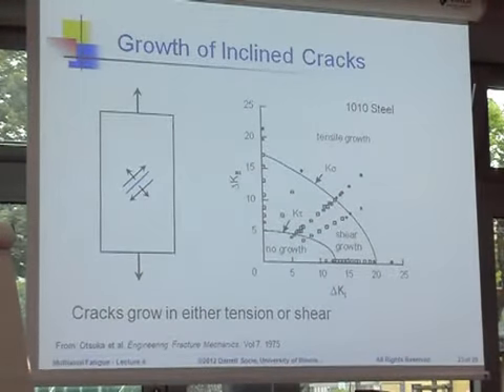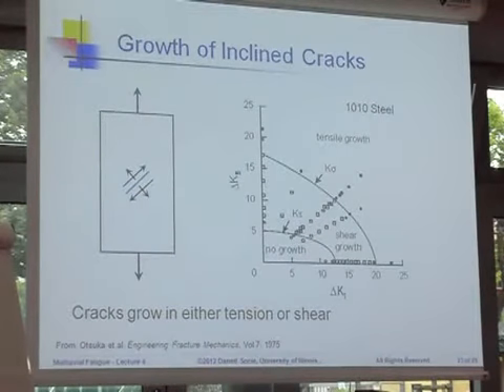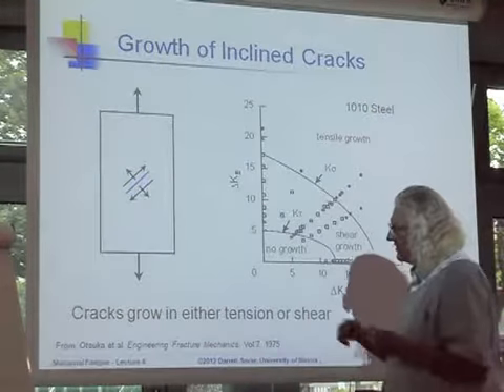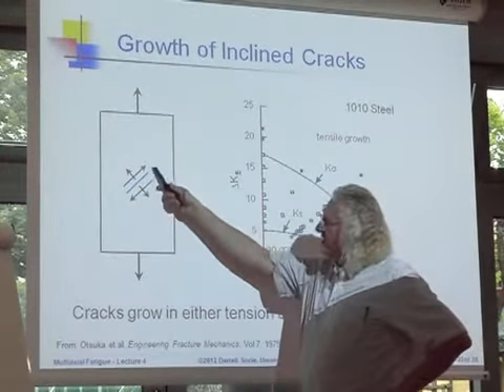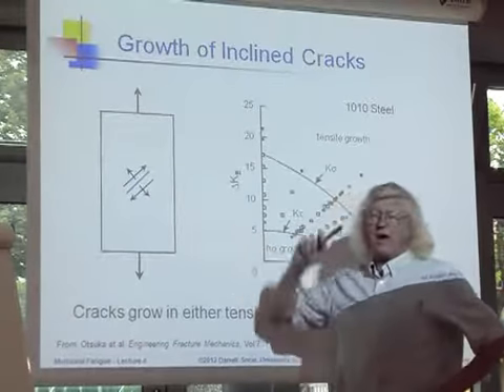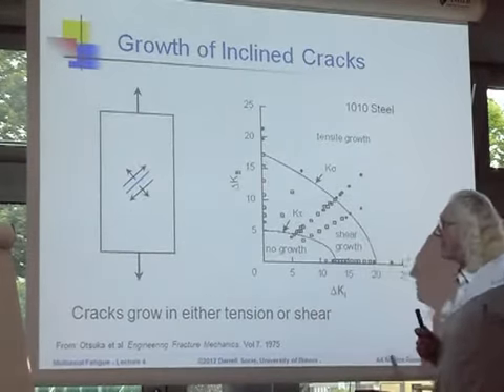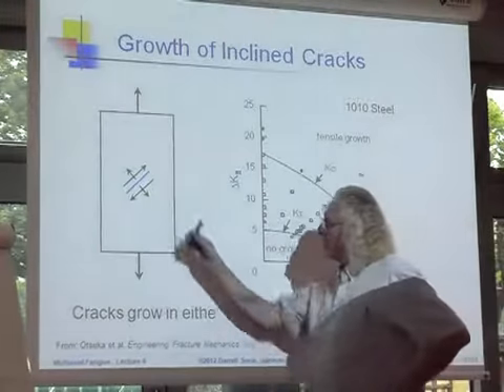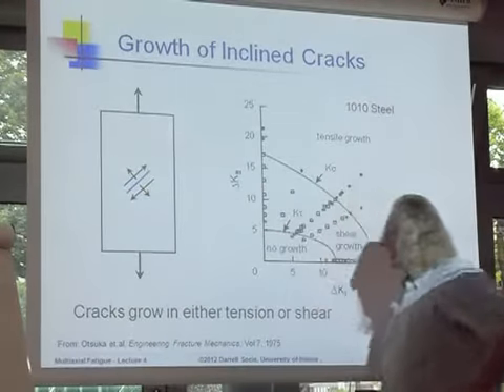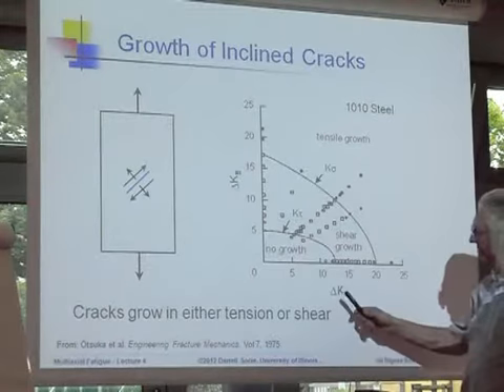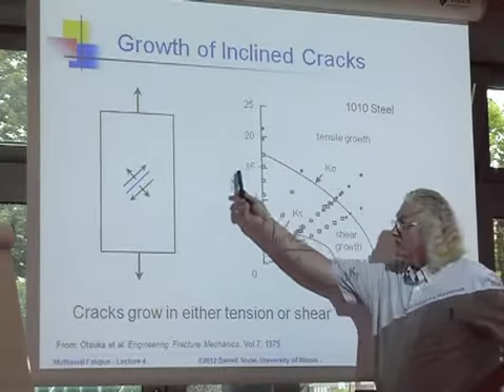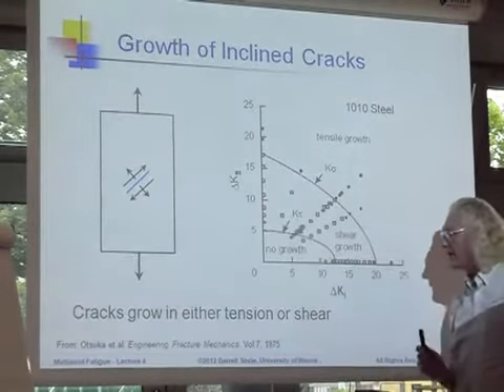I don't know how useful that is in a real situation, but it's easy to study analytically and experiment. And this is the best data, and you can see where it comes from. Otsuka has the idea that cracks try to grow either in tension or shear, and so you can see why I am attracted to this work. Depending upon the orientation of the crack angle here, you can get different orientations of mode 1 and mode 2, so we just plot K2 and K1.